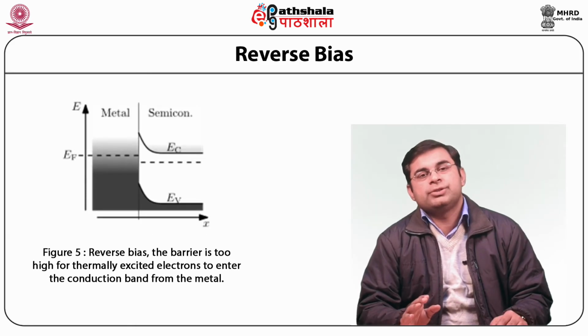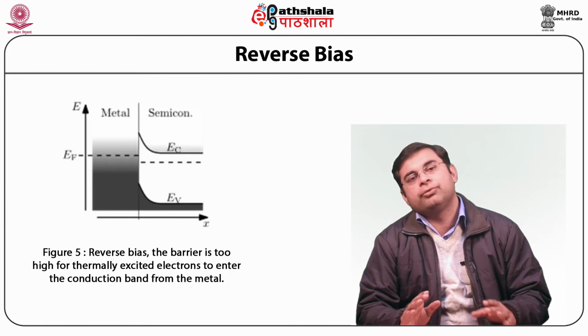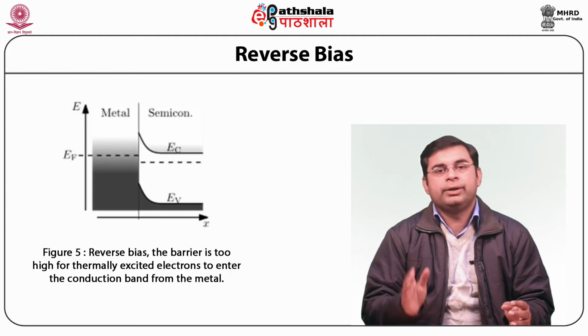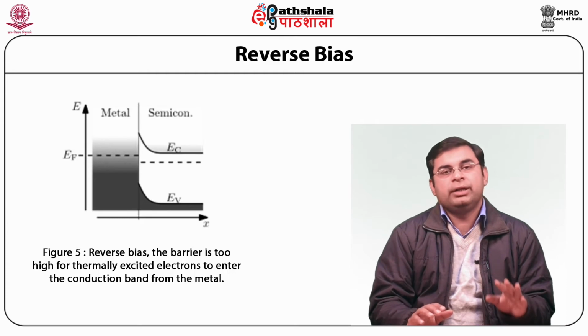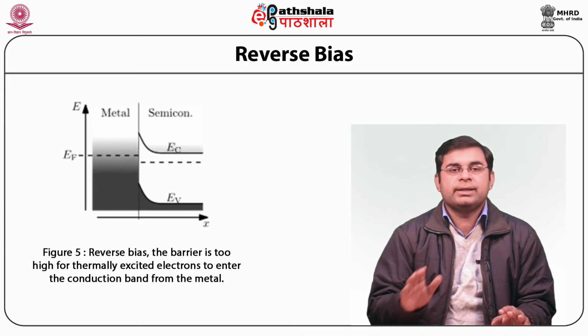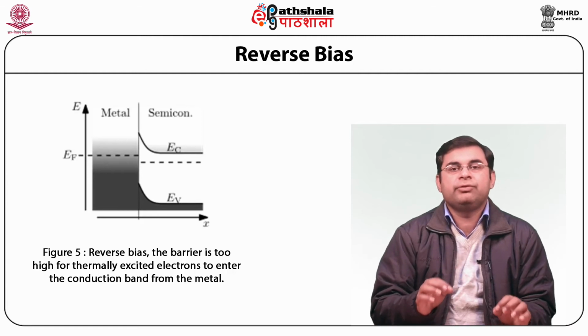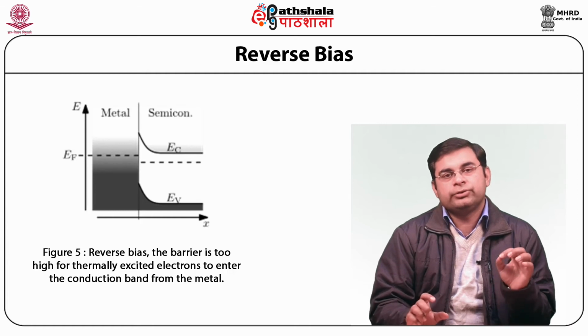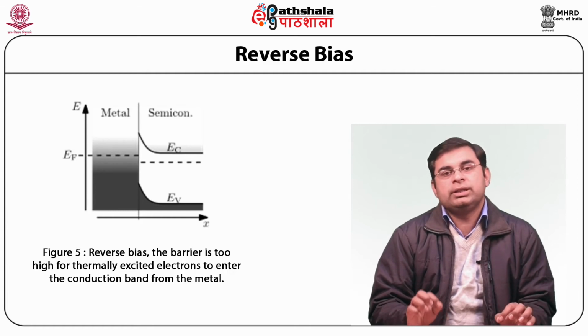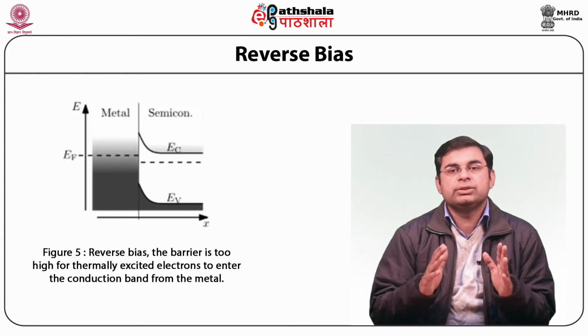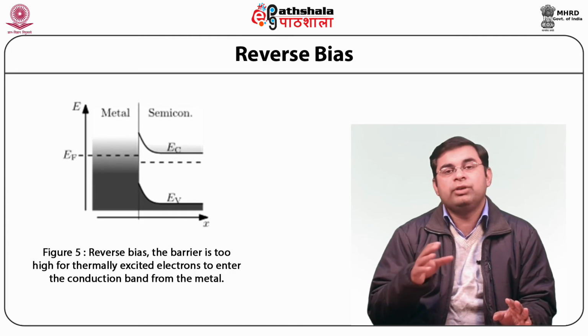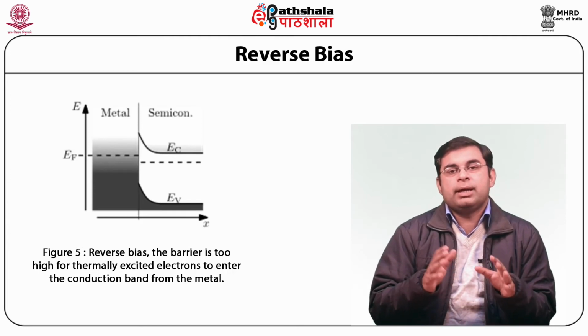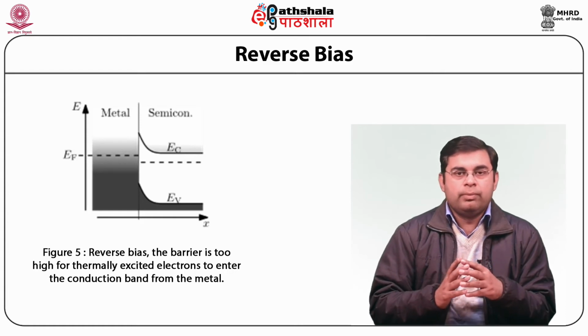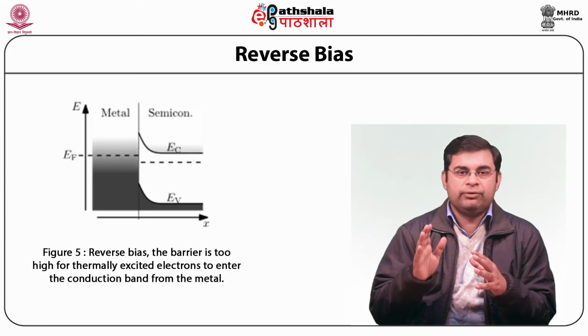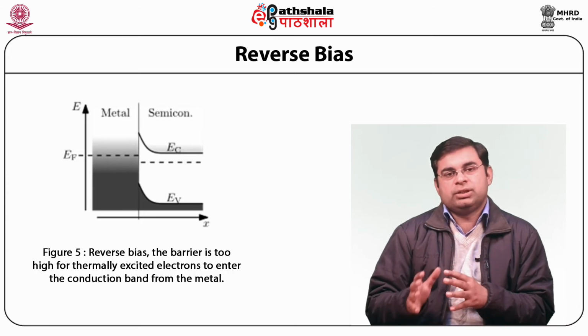Reverse bias. As shown here in figure 5, in reverse bias, the barrier is too high for thermally excited electrons to enter the conduction band from the metal. Under reverse bias, very few thermally excited electrons in the metal have enough energy to cross the barrier. Thus, a small leakage current flows. This leakage current is not constant but gradually increases with reverse bias voltage, owing to a weak barrier lowering, same as the vacuum Schottky effect. However, when reverse bias is increased to higher values, the depletion region breaks down.